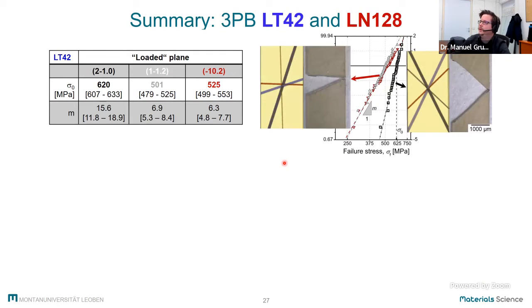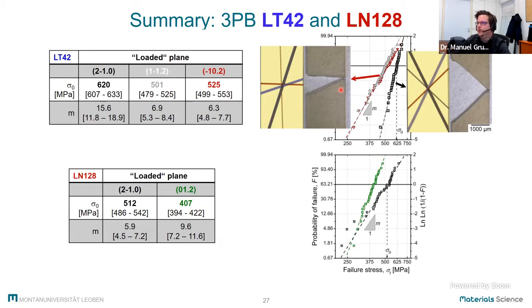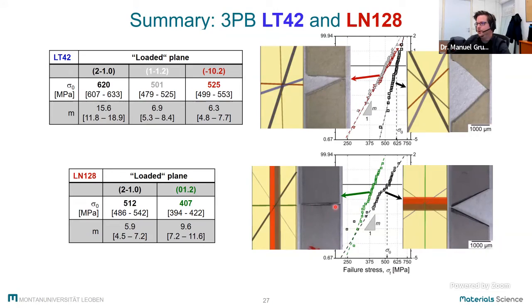And again, we selected two different orientations. So one orientation with the cleavage plane perpendicular to the highest tensile stresses, and a different orientation where we expected higher strength values. And if we compare the results, we can see indeed that we get the lower stresses for those specimens where the cleavage planes are perpendicular to the highest stress values. The same we did for lithium niobate, and again, we can see that this unfavorable orientation leads to lower strength values and thus a lower reliability of the material. All of the fractures initiated at the edges of the material, and this can explain the lower strength values compared to the biaxial tests I showed you before.